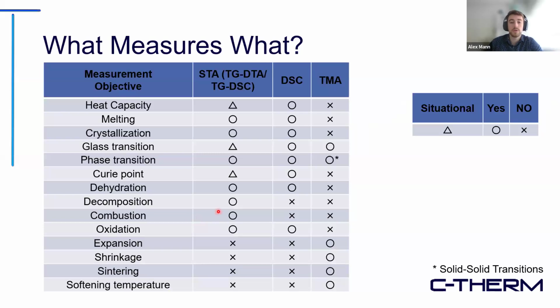So first off, what measures what? Starting off on the right, we have TMA. This is great for measuring expansion or shrinkage due to different temperature changes. So from this, we can measure glass transition, phase transitions if they're solid-solid, as well as expansion, shrinkage, sintering, even softening temperature. This is great for packaging materials to test their expansion, their shrinkage, or if they have a low or a high CTE, which can impact how stable they are at different temperatures, as well as softening.